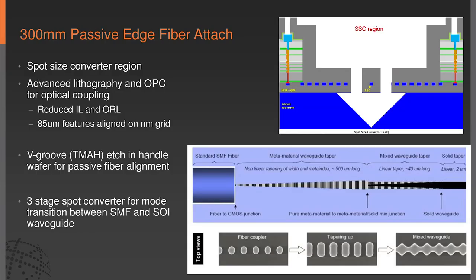I want to spend a little bit of time on fiber attach. There's a big debate in the industry—do you do passive fiber alignment, active butt coupling, or grating couplers? We are holding the course and leveraging V-groove technology. We form a V-groove using a combination of etches through our back-end stack, then use TMAH to get the crystallographic etch. If you get the right dimensions, you'll center your 8-micron core fiber on the waveguide. It's basically a mode converter taking the mode from 8 microns down to a single 350-nanometer mode over several hundred microns. The 300-millimeter lithography really comes into play here because all the spine, rib, and post dimensions are very critical.